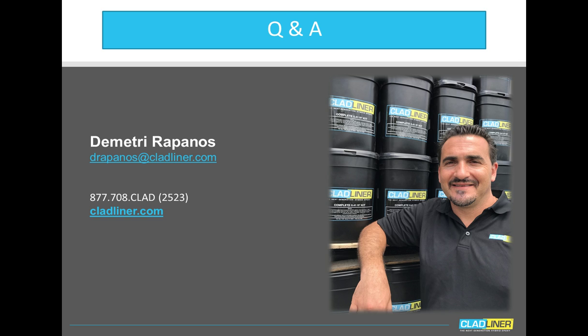Because the cementitious, or should I say the hybrid epoxy, is so similar to the cement in some of its properties, the spark tester would read the epoxy liner or the hybrid epoxy liner as part of the concrete substrate behind it. However, because the product itself, as you can see by the color, is a rich blue color, and it's typically being applied at a 1/4 inch, the thickness can be measured using a wet film gauge during application. It is quite easy, because of the color difference, to see whether we have any holidays or discontinuous areas when the application is complete.